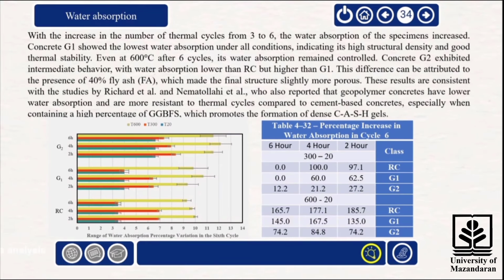With further cycling from 3 to 6 cycles, all specimens exhibited additional increases in water absorption. Among them, G1 consistently showed the lowest values. Even at 600 degrees Celsius and after 6 cycles, its absorption remained controlled.